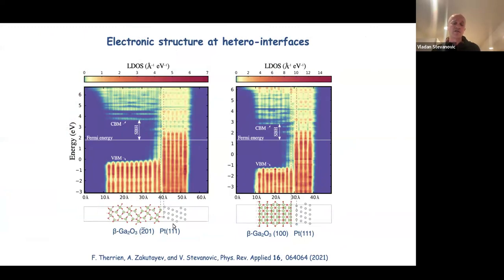So this is the local density of states on one of those interface structures, calculated using hybrid functionals, so the HSE functional, a little bit better representation of band gaps. And you recover Schottky barriers that are very close to experimental results using these techniques.